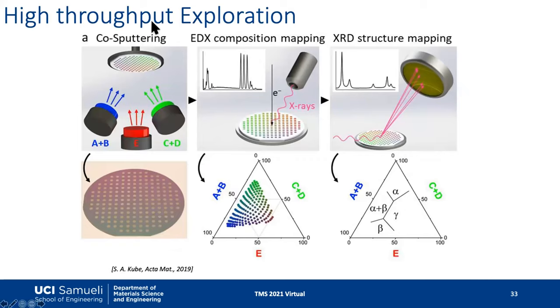One technique is the high throughput technique by using sputtering, co-sputtering, where the target is as shown here, and you can see that you can have various different alloy systems. Essentially, very quickly, one can have many, many different alloys prepared on one sample to do the triage, if you will. But I think also a lot of simulation where one can reduce the number of alloy systems from however thousand of number of alloy potential candidates, and then make the samples by this technique.